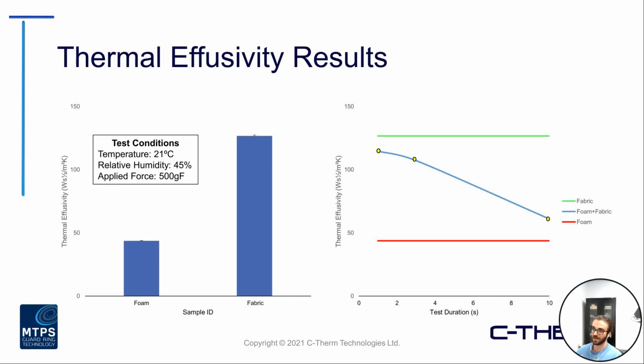So that initially higher effusivity top surface is being more and more influenced by the foam on the underside as the measurement duration increases. And this may give you some very interesting data with respect to how you're stacking the samples, the thicknesses of those top layers and how the bottom layers are influencing and interacting. And again, just different things that can be done, all with the MTPS sensor, just by modifying the different test conditions that are used for your measurements.